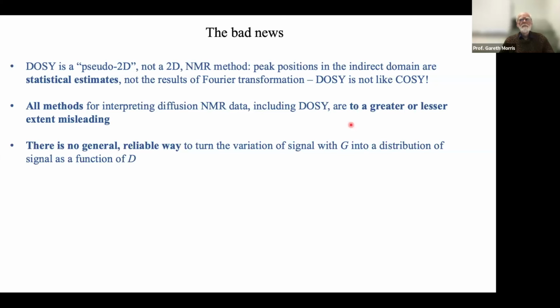In many ways, the tragedy of DOSY is that there is no recipe for taking an experimental signal decay as a function of gradient and inverting that to give a distribution of signal as a function of diffusion coefficient. We can't get the equivalent of GPC or looking at polymer size distributions with any degree of safety or reliability.